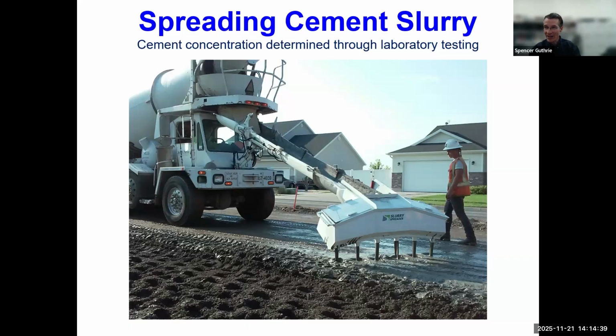Then, to get a nice even distribution of the cement, we invented the slurry spreader. The slurry, a mixture of the cement and water, flows right through the cement or the concrete chute into the spreader basin and then exits those 6 nozzles that you see. And it can be readily applied in an even, uniform fashion, even in a residential neighborhood. So you see that nice green lawn of the home across the street.